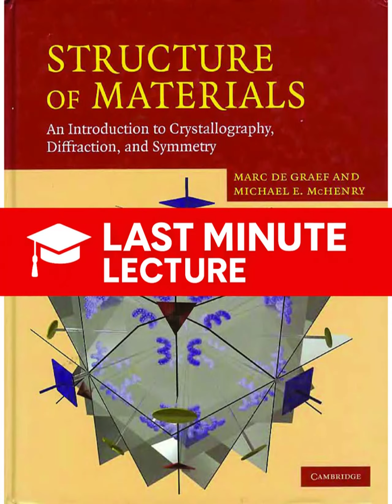When does that happen? When do you get that perfect maximum value? Only during what we call forward scattering. That's when the scattering angle theta is 0. So straight ahead. Straight ahead. If the X-rays are scattered directly forward, the path difference between waves scattered from any electron in the cloud, from the inner shell to the outer shell, is 0. They all add up perfectly constructively. So at 0 degrees, f equals Z. It is maximized and exactly equal to the atomic number.